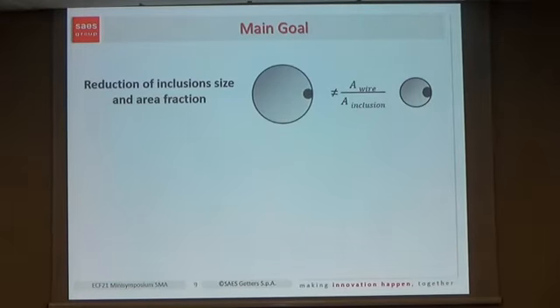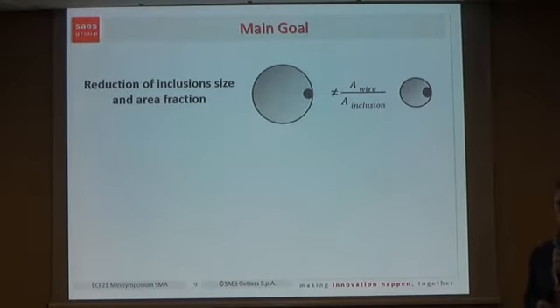We are talking about very, very thin wires. And what is the problem? The problem is that inclusions become bigger and bigger relative to the cross-section of the wire as we reduce its size. So we had an industrial motivation to improve the fatigue of our materials, to allow faster growth of the industrial application, for example, what I reported in the previous slides.